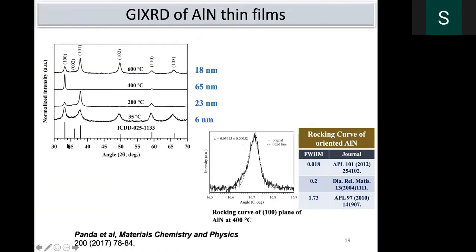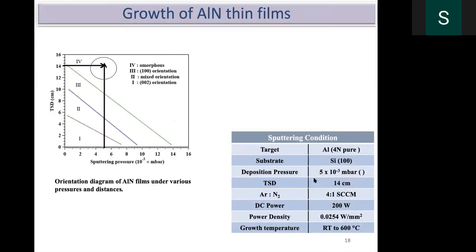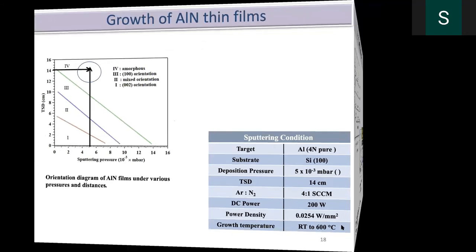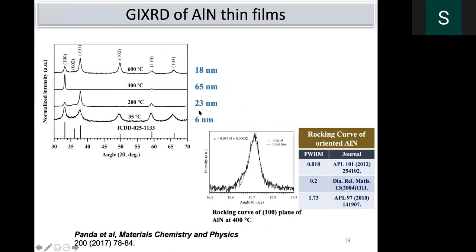Well, what we have done is we have kept all other conditions constant, as I told, the deposition pressure and target to substrate distance. Now we have varied the temperature alone, from room temperature to 600 degrees centigrade. You can see the growth of crystals up to 400 degrees centigrade. After that, the crystallite size becomes 18 nanometers. You will get a question how and why. The reason is resputtering takes place at around 600 degrees centigrade, which is not possible up to 400 degrees centigrade. That's the main reason.